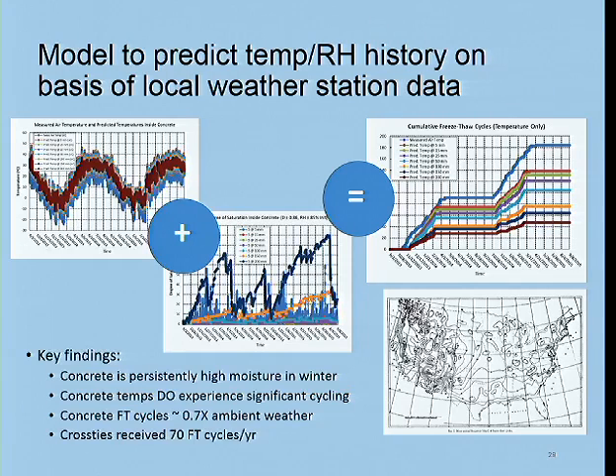You see the top line here is the freezing events of ambient conditions, just the temperature data. How often did we go through a freezing event? And these next ones are how often different points of the tie itself felt this, at different depths inside the tie. This one's closest to the skin, and these are most interior to the concrete tie. This gives us the basic finding that concrete is persistently high moisture during the winter times. Concrete temperatures do experience significant cycling, and we see a relationship between the weather station versus what the tie feels of about 0.7. So 70% of the time that your weather station data says you've undergone a freeze-thaw cycle, the tie material itself feels it. Otherwise, there's sort of a damping of those things.